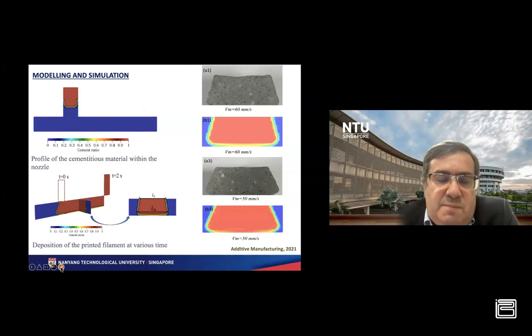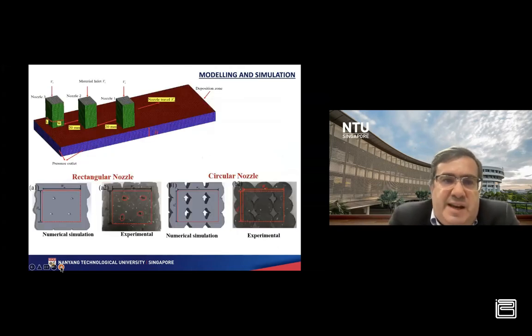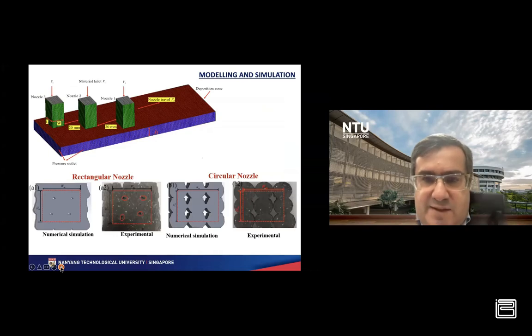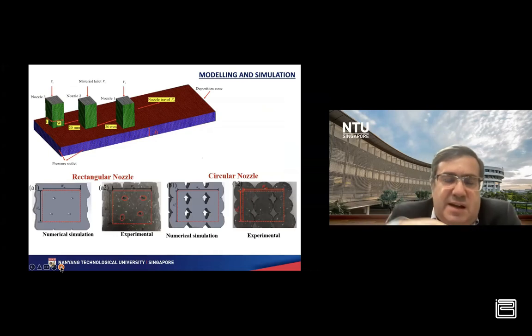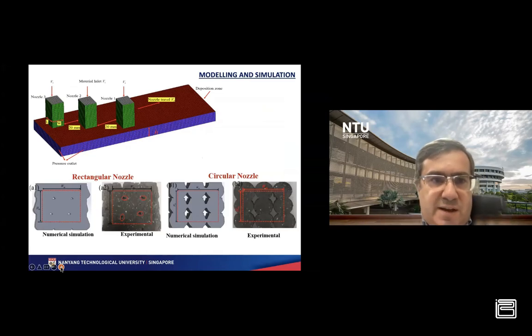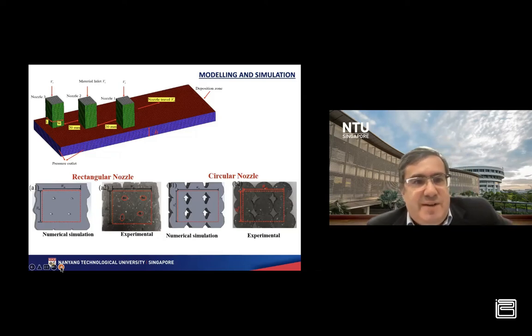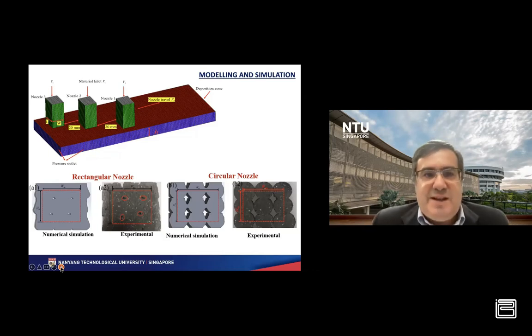We are using also modeling and simulation to predict internal defects, as shown in this slide. So this corresponds to a simulation considering multiple printing layers using different nozzle configurations. As you can see, again, there is a high agreement between predicted results and experimental results, even if we consider, for example, circular nozzles and not really optimized processing conditions, which create significant internal defects.